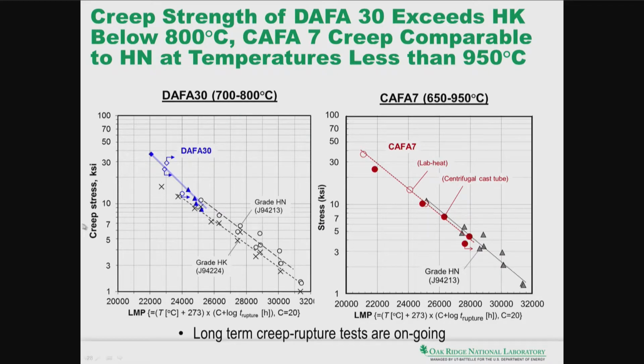So we are also accumulating creep data. We are still in the process of having more tests added to this as we speak. But what we show here is the Larson-Miller plot for DAFA 30, and also superposed on that are the HN and the HK data. And you can see that the DAFA 30 performs comparable to or better than the HK at temperatures up to about 800 C. Again, remember that at temperatures above 800, close to 900, the strength is going to drop off pretty rapidly.